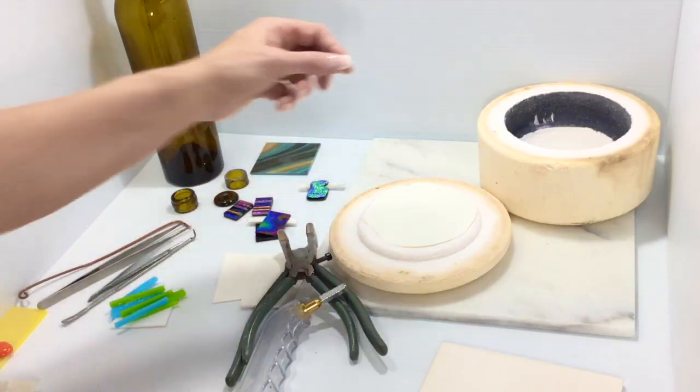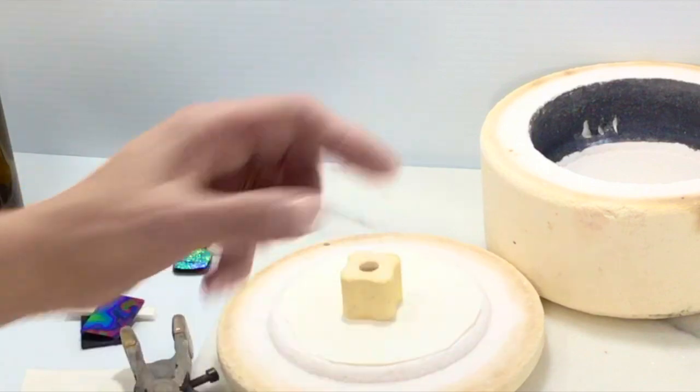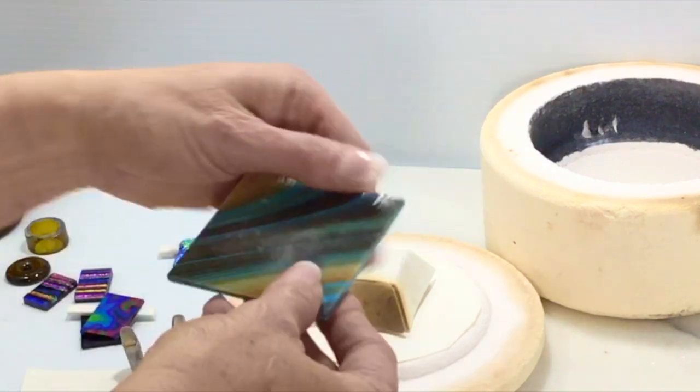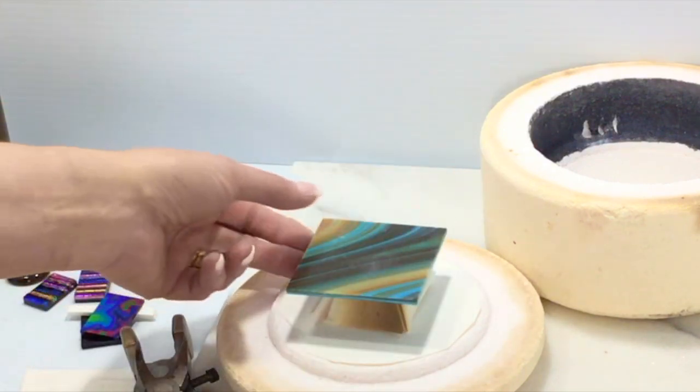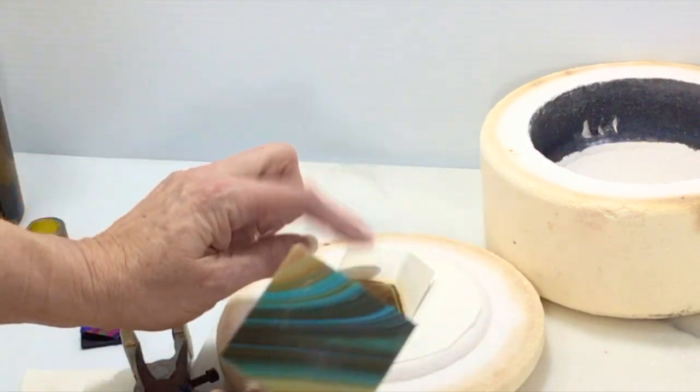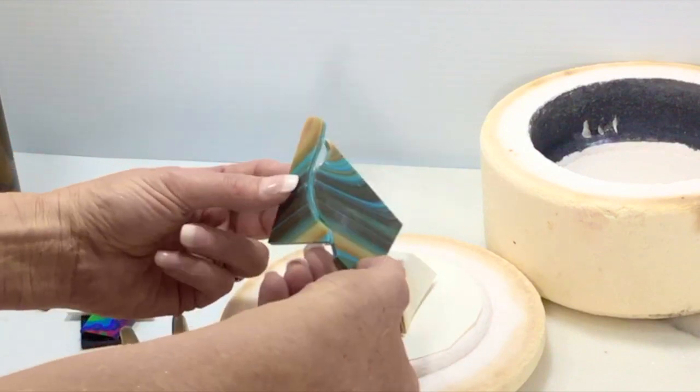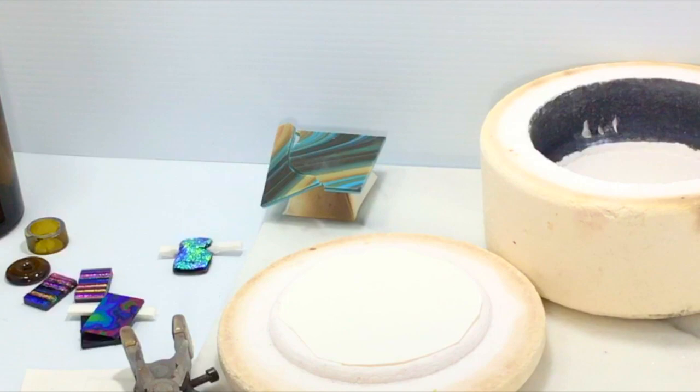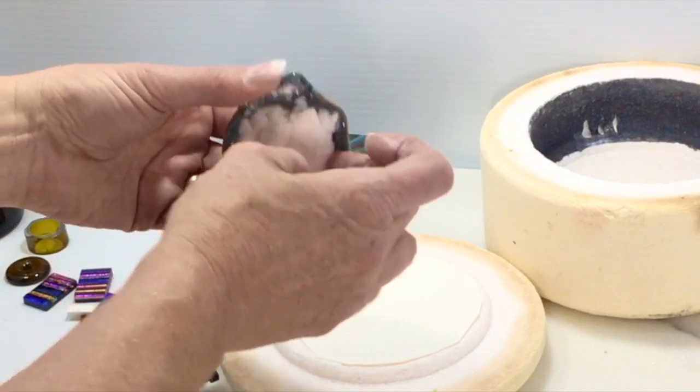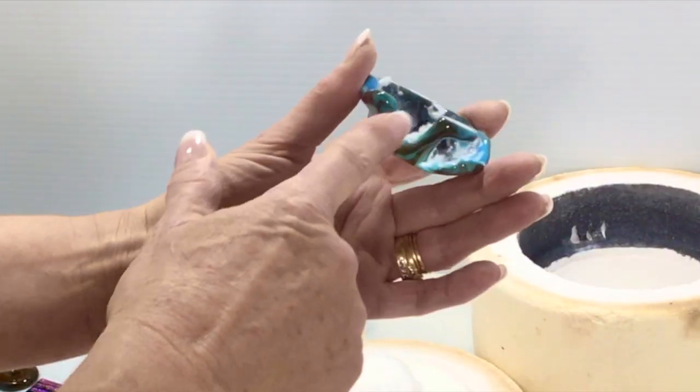Another option is slumping. And I'll tell you, I tried a couple of things with this. I put a little kiln brick there. And I put 16th inch fiber paper on top of it. And I thought this will be a nice slumping mold. What happened was the heat built up too quickly. I think because of that brick underneath it. And it cracked. So I thought about that again. And I did a little fiber mountain. A little teeny one. And I teetered the glass on top of that and let it slump over. But I went a little too hot and ended up with this little leg. So again, I'd want to perfect that firing schedule if I was using my microwave kiln regularly.